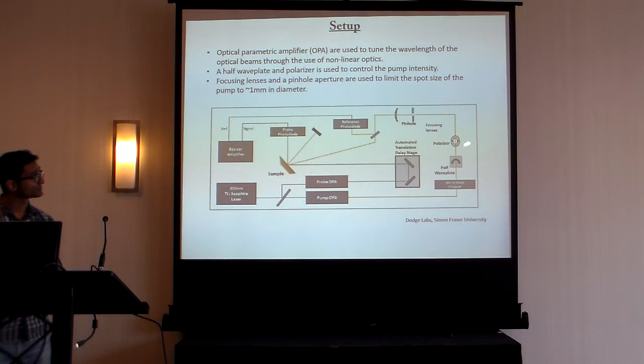The pump then goes through a half-wave plate and polarizer, which allows us to adjust the intensity of the beam, and then goes through a pinhole aperture and focusing lens, which limits the beam width to approximately 1 millimeter over the entire spectral range. Part of the beam is picked up by a reference photodiode, and a large portion is incident onto the sample, creating the non-equilibrium states. The probe beam is sent through an automated delay stage, and it's reflected off the same point on the sample and picked up by a probe photodiode. Both signals are sent to the boxcar amplifier, which gates and averages the pulses.